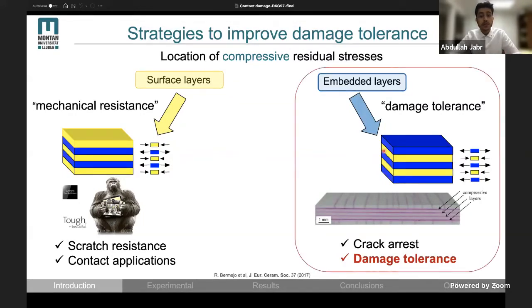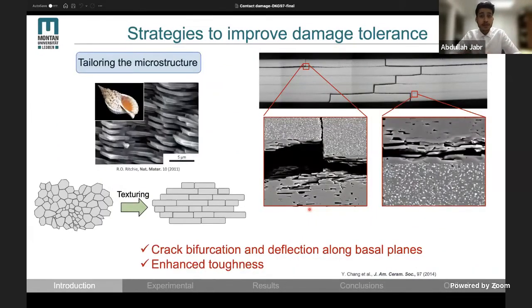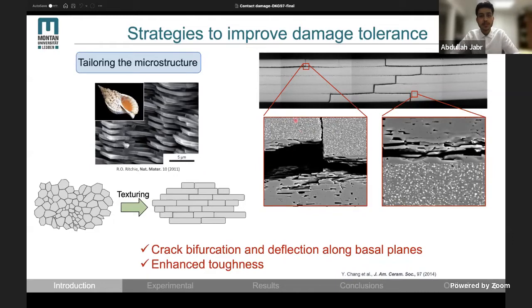In this work, we followed the damage tolerance approach. Here the material can tolerate the presence of surface defects by arresting crack propagation at the internal layers. This has been shown in previous works on the example of thermal shock tests. My hypothesis was that this could also be very effective against the propagation of surface contact damage. There has also been extensive research on tailoring the microstructure by taking inspiration from the mollusk shell, where hierarchical architectures can be replicated by microstructural texturing, proven to be very effective against the propagation of surface cracks.